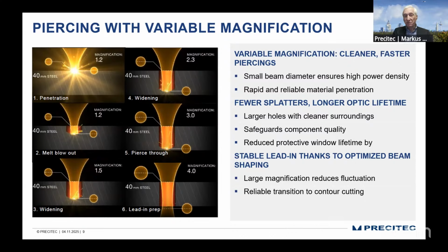We have a lot of software in the Cutbox Pro, which is the system which is connected to every cutting head. And one important thing, for example, is that we vary the magnification during the piercing process. You see here from step number 1 to step number 6 how a piercing process in thick section steel, this is a 40mm steel sheet, works, where we start from a magnification of 1.2 to a magnification of 4.